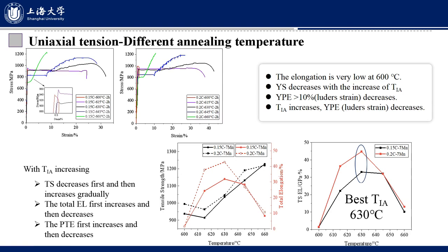annealing condition. And the yield stress decreases with the increase of intercritical annealing temperatures. Yield point elongation is larger than 10%, but with temperature increasing, the yield point elongation decreases.